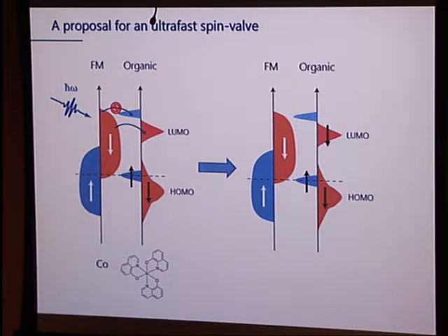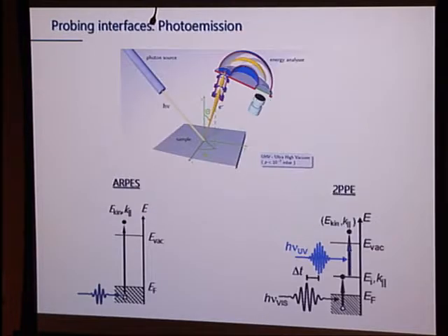Exactly. So this is not the full spin valve, right? We removed the top electrode. We're just going to look at the spin filtering aspect of cobalt with ALQ3 on top. No, much thinner. One of the aspects that photoemission gives you is that it is very interface sensitive. It can only probe a very small area, depends on your energy range, but say no more than a nanometer. So this allows me to really look at the interface and the interface only.